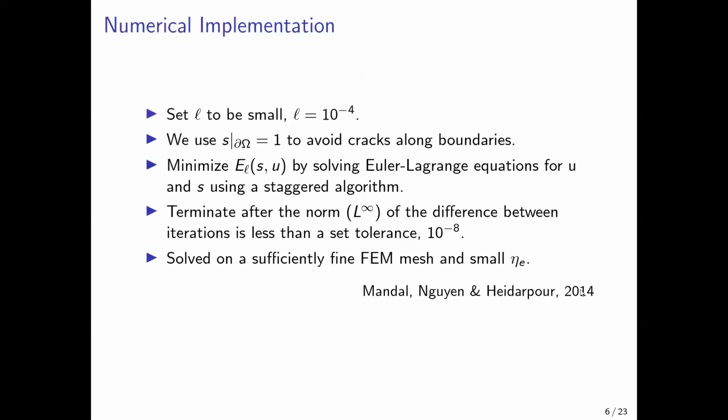So for our numerical implementation, we want this regularity parameter L to be fairly small so that we're close to the problem of the original crack set. And we also want S to be 1 along the boundary to avoid premature nucleation of cracks along the boundary.